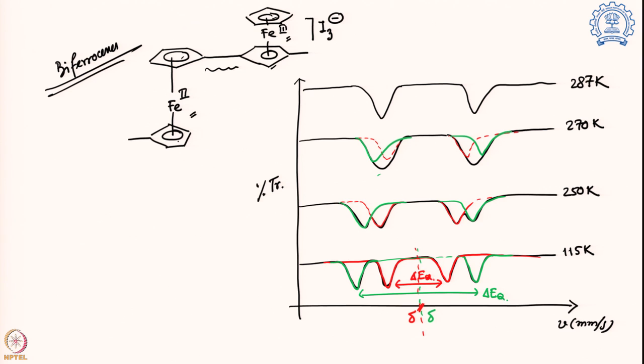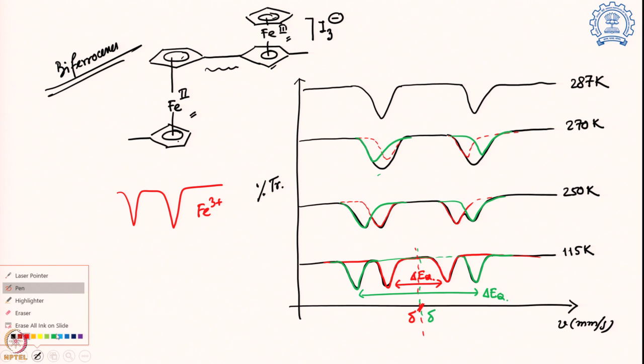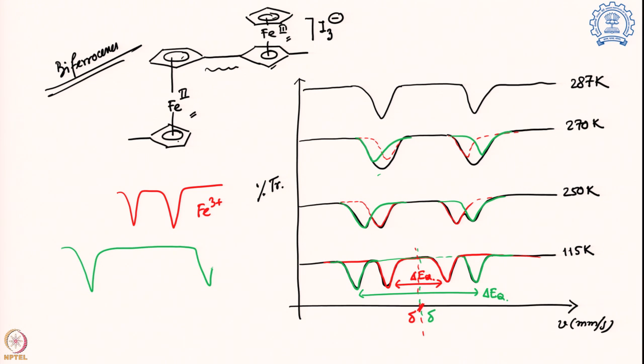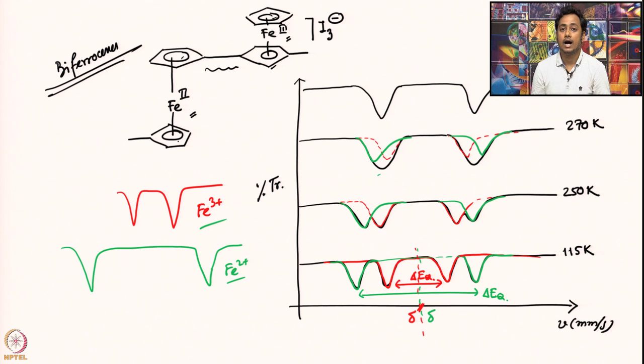Getting our knowledge from the ferrocene-ferrocenium system, we then defined the red one, the closely lying system, as from iron plus 3, whereas the well separated system is from iron plus 2. As we already know, the ferrocene, the iron plus 2 system, is well separated because of its higher electric field gradient. Whereas the ferrocenium one is much more shrunk down, and that is why the lines are close.